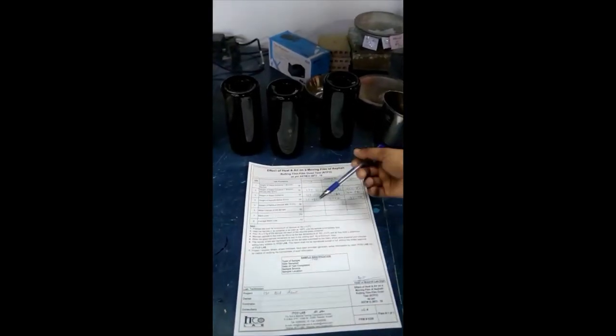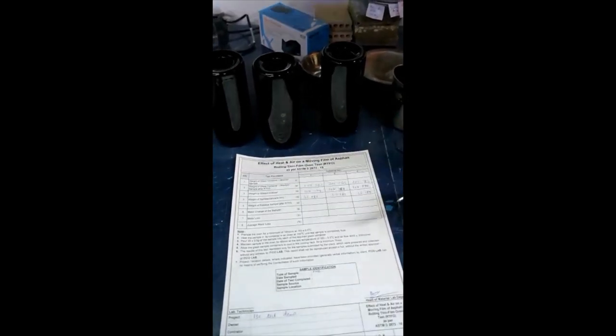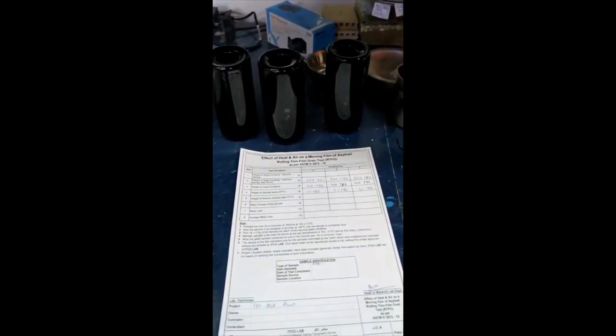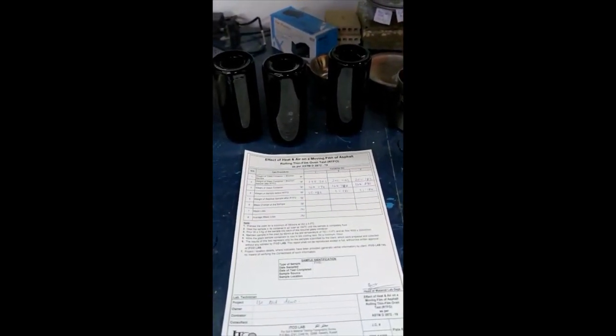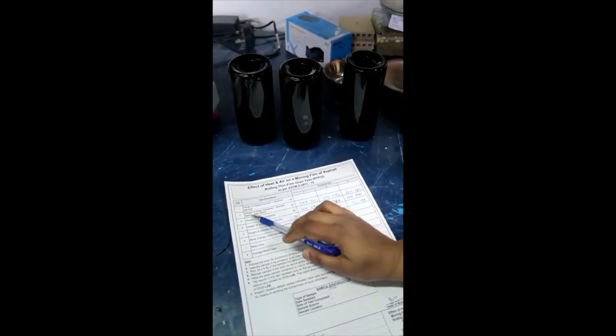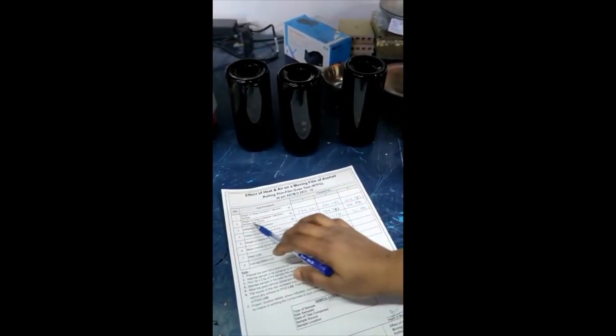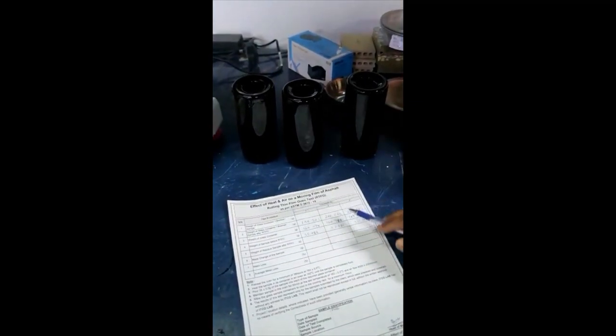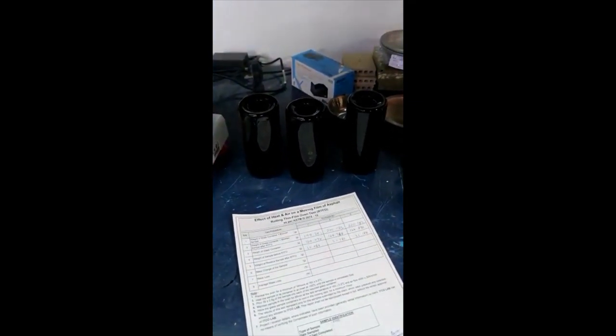After 85 minutes from the start of the test, we removed the glass container from the RTFO. Then I kept it for cooling at room temperature for around 1 hour. Then I took the weight of the glass container plus bitumen sample after RTFO. This I took for determining the mass loss.